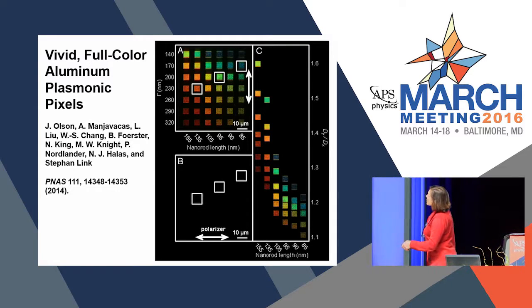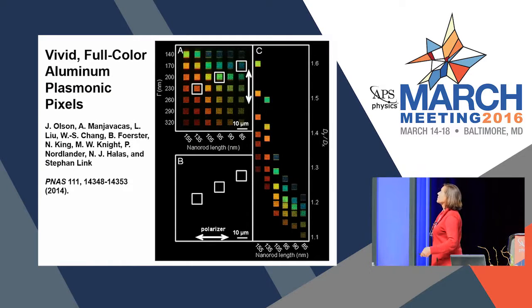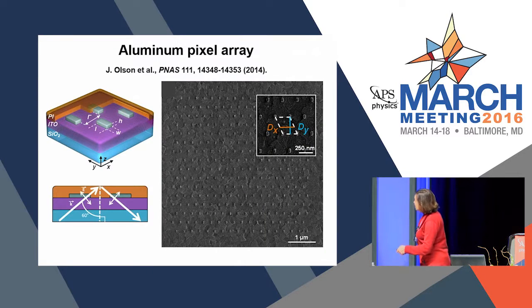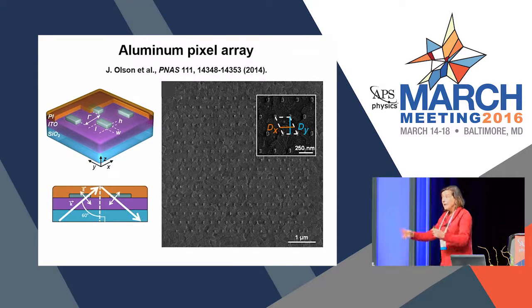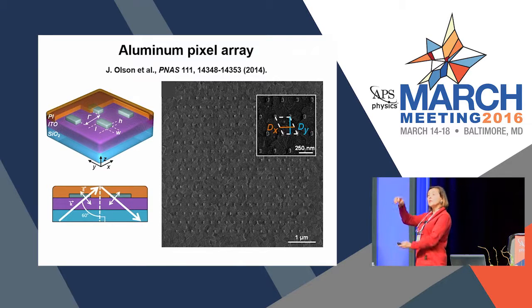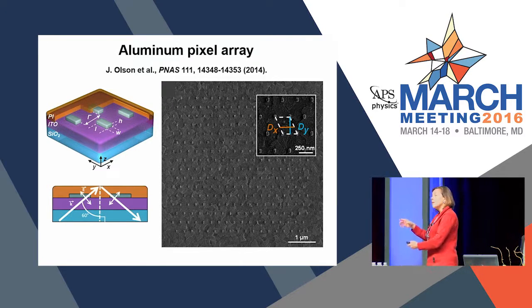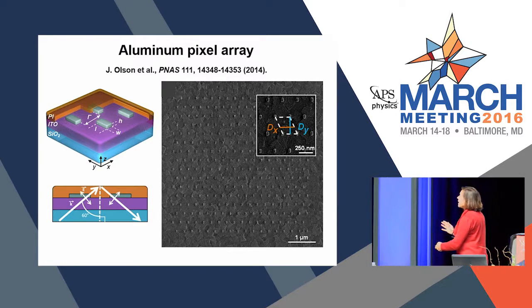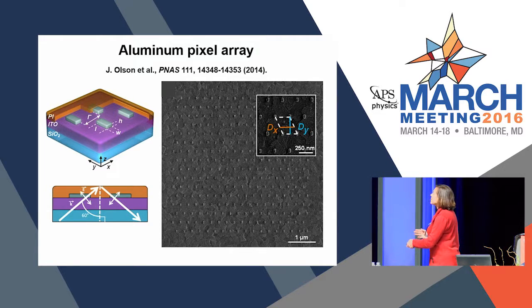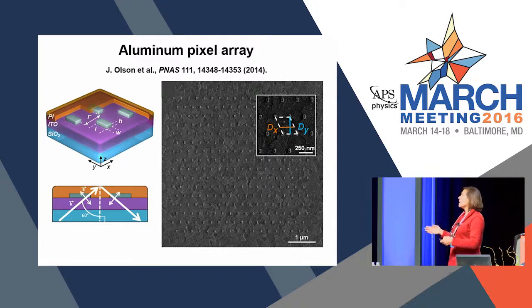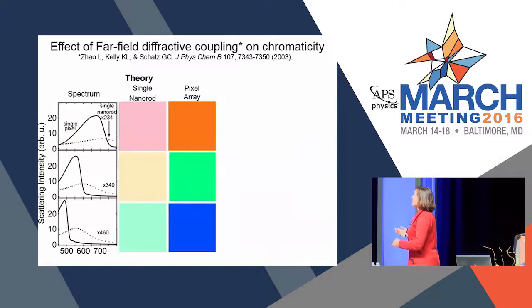So what I'm showing you here are a range of different pixels that are very vivid that are all made out of aluminum. And so one has aluminum nanorods, as you can see here. The secret to the vivid color that I just showed you is the fact that you have nanorods and you can tune the color by the aspect ratio, but you also can make them vivid by formulating the nanorods all oriented in periodic arrays. And so you use both the periodicity of the array and the optical effects that you can obtain, plus the nanorod resonances, to give you very sharp, vivid colors.